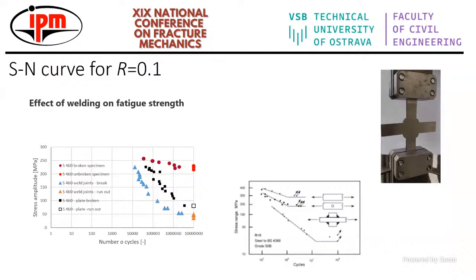Okay. Then we move to the important results, which were performed on these joints, and now you can see 3 results. The first one is well known from the circular specimen. Then we prepared the measurement on the plate, and then the plate with weld joints. You can see that each geometry changes the fatigue behavior of the material, especially when we look at the endurance limit, which is 1 × 10⁷.